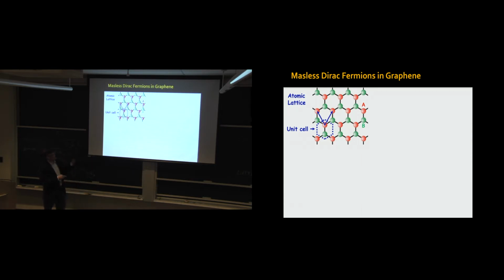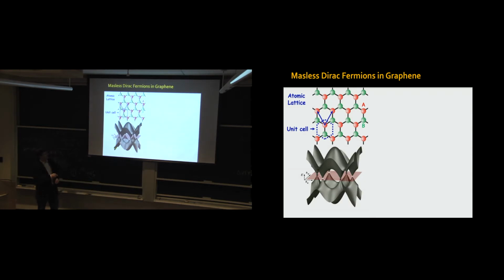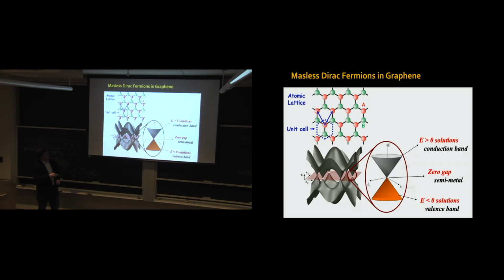So you can calculate, in a simple quantum mechanical model, what is the electronic structure — the energy versus momentum for the electrons in graphene. It turns out to be like this. This is your reciprocal space, your Brillouin zone, and if you zoom in near the corners of your Brillouin zone, you have this very peculiar energy-momentum relation, which is linear. Usually you have parabolas for your kinetic energy, but in electrons in graphene you have this linear energy-momentum dispersion, which has led to all these analogies with ultra-relativistic massless particles for electrons in graphene.